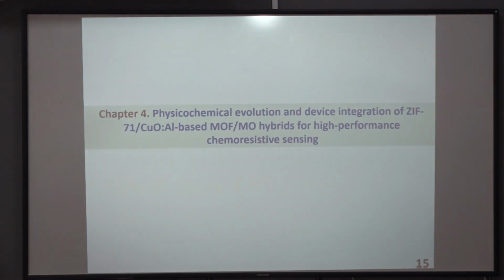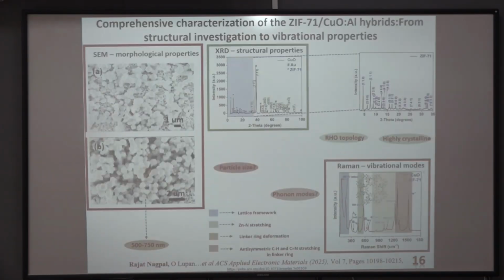Followed by this chapter, which includes physicochemical property studies about ZIF-71 copper oxide aluminum hybrids and device integration and its performance for chemoresistive sensing. Here we can see from the SEM image partial coverage of ZIF-71 particles on copper oxide and full coverage. It gives insights about the morphological information, rhombic dodecahedral morphology we can see, and particle size estimation.